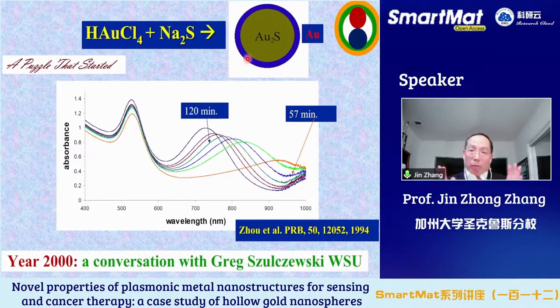And I didn't know this either when we started, 22 years ago. But I can tell you today, if I know what I know today, this is wrong. That assignment cannot be correct. Because if you have truly a completely degenerate core shell structure like this, you should see one peak, not two, as I'll show you today. But in 2000, I did not know that. Greg didn't know either. We didn't know the theory behind it, but he knows that experimentally, he did not see any core shell structure.